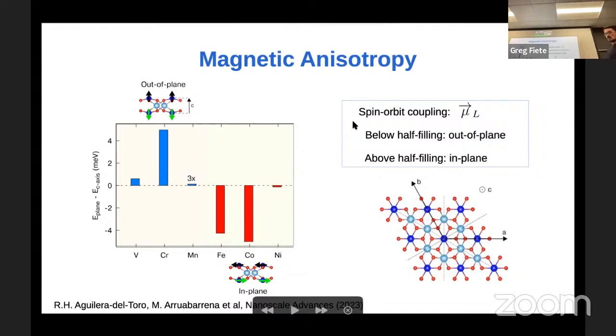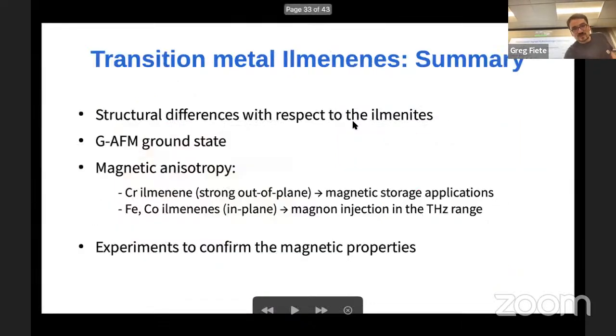So all in all, I think this is the summary of the part. Ilmenines, even though they have similarities to the ilmenites, have some crucial structural differences with respect to them. They have an AFM magnetic ground state, while some of them also present a large magnetic anisotropy, both out of plane and in plane, depending on the compound. So for example, chromium ilmenine could be interesting for magnetic storage applications, while iron or cobalt ilmenines, for example, for magnon injection in the terahertz range.